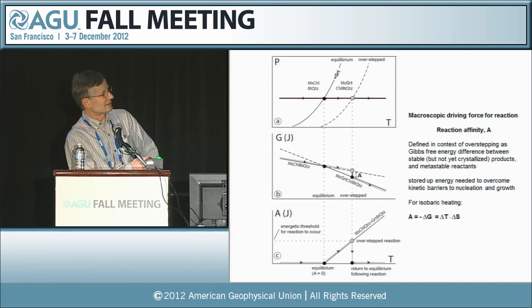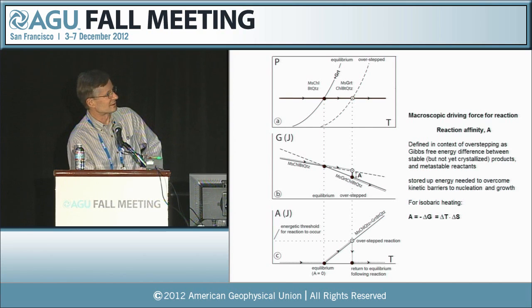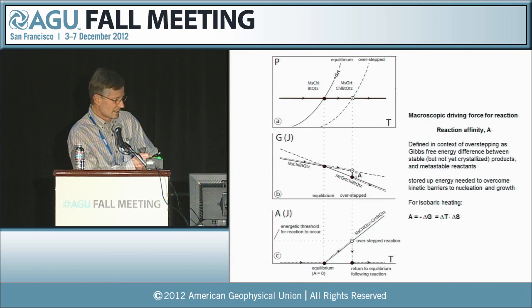If we overstep that, that can be understood in terms of this GT diagram. So this is the GT surface of the reactant assemblage, and this is the GT surface of the garnet-bearing product assemblage. And where those two intersect is the equilibrium position of the curve, which is the black line up here. Now, if the reaction does not go as expected, if there's overstepping, then one extends along this dotted line, that metastable extension, and then eventually, once a reaction goes, then the system drops back down to the stable configuration. But in the intervening overstepped interval, you can see that the difference between these two lines gets bigger and bigger, and that energy difference is the reaction affinity. In situations where there is thermal overstepping, the reaction affinity is simply equal to the temperature overstep times the entropy change of the reaction.